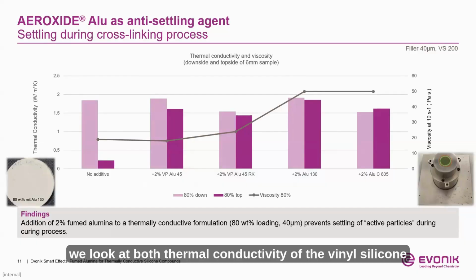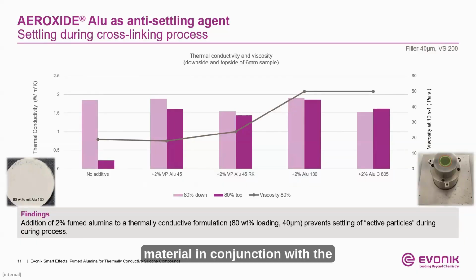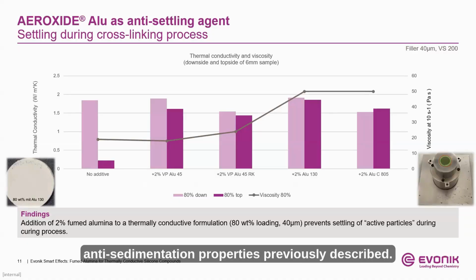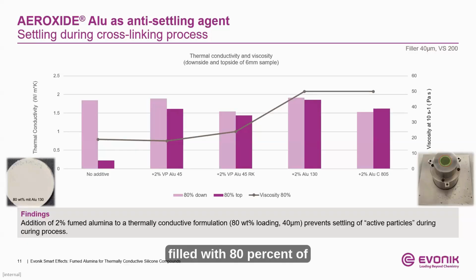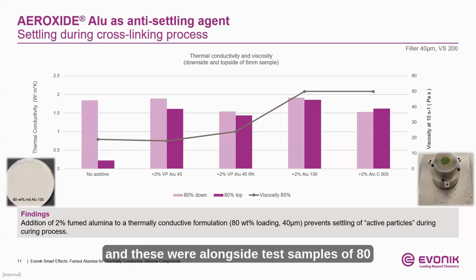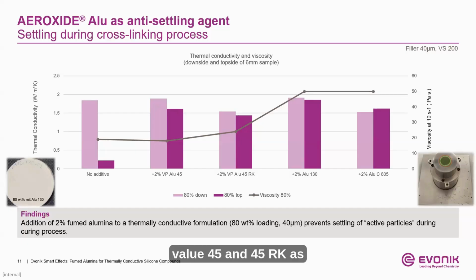Finally, we look at both thermal conductivity of the vinyl silicone material in conjunction with the anti-sedimentation properties previously described. Here again, we cured a 6 millimeter disc. You could see it on the left of vinyl silicone filled with 80% of the 40 micron spherical alumina. Again, this was our blank sample, and these were alongside test samples of 80% spherical alumina with an added 2% of a variety of our fumed alumina grades here, the VP Alu45 and 45RK, as well as the Alu130 and